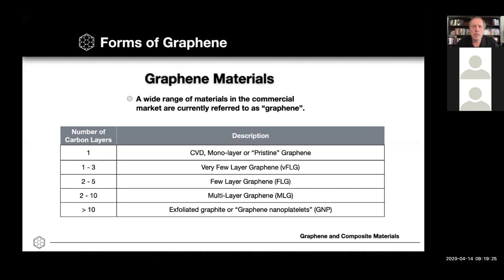And so when we look at materials again, you'll hear many people talk about, well, we're offering you graphene, but the real question is, what exactly is the material you have? And then it needs to be characterized. And I'll let you know that we are going to be having another webinar later in the month with the National Physical Laboratory out of the UK on material characterization. So that's another important topic that we'll cover in a few weeks. So you have a single layer of carbon material, which could be referred to as monolayer or sometimes called pristine graphene, to different numbers of layers of graphenic material. And then you also have issues of distribution, so that if you receive a graphene material, it may be that 80% of it is between 2 and 5 layers and 20% of it's between 7 and 10 layers, for example. So that's another nuance to the type of material you get.